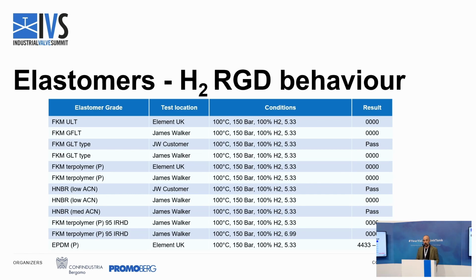And we saw that we can't make the comparison between helium and hydrogen, even if the hydrogen molecule is very similar to helium in terms of hindrance and polarity, and in a lot of characteristics. But helium doesn't cause RGD damages. We saw that hydrogen actually can cause RGD damages, and we can say that it's quite similar to the standard Norsok test, which has 10% of CO2 in the supercritical state. So that's an issue.